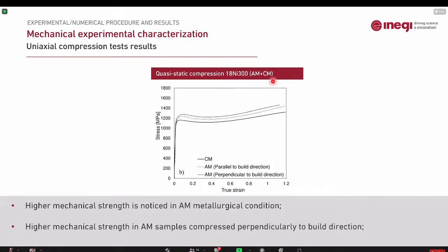The results from the quasi-static compression test show the typical results that we can see. The additively manufactured steel presents higher strength, and within the two distinct directions of the additively manufactured compression, we noticed that one of them has higher strength, which is related to the columnar grain formation.